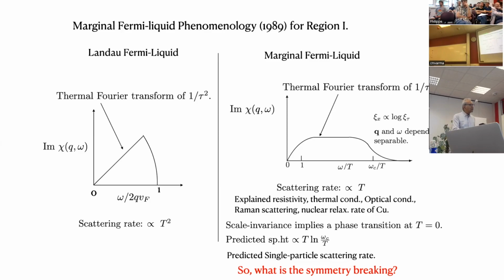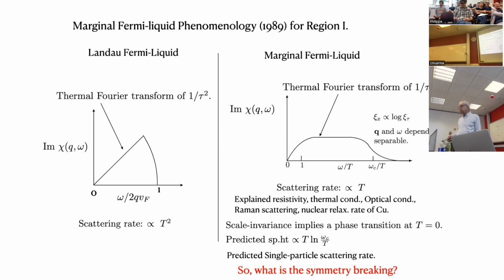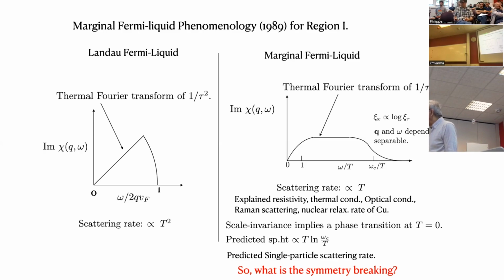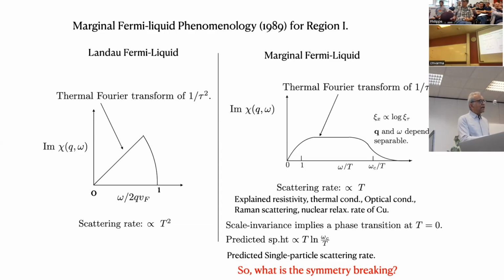And then there's this cutoff. And all Landau theory basically does is to give you, for different response functions, slightly different slope, which can be related to the Landau parameter. But the fundamental fact is already evident in the non-interacting theory, that due to limitations of phase space by Pauli principle, the spectrum decreases. Now, this, by general causality, has to be an odd function of omega, so sort of going like that. And given this, you can calculate the scattering rate of fermions.